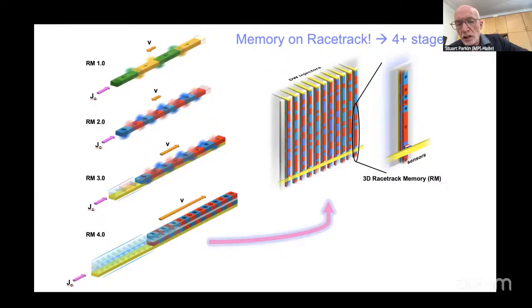And the magnetic walls, these are vortex or transverse walls, can be moved by passing current through the magnetic material through this spin transfer torque. Okay, so in the case of soft magnetic materials, the domain walls are very, very wide because the domain wall width is related to the strength of the magnetic anisotropy and the magnetization. So if the anisotropy is very weak, then the domain walls would be very, very broad to minimize the exchange